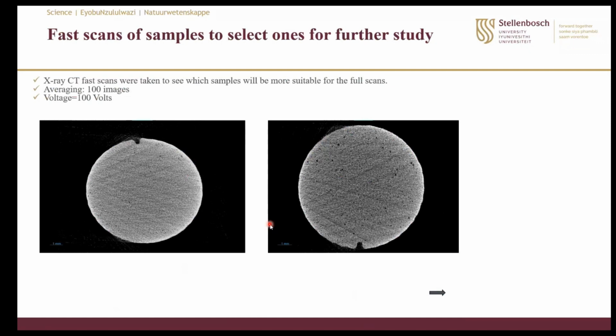Even though most studies find that when they preheat their base plate, they tend to get less porous samples as the temperature increases, with me, I've got the opposite. The porosity levels increase as you move from the lowest preheated base plates to the highest preheated base plates. This is mainly caused by the fact that laser powder bed fusion is nonlinear.